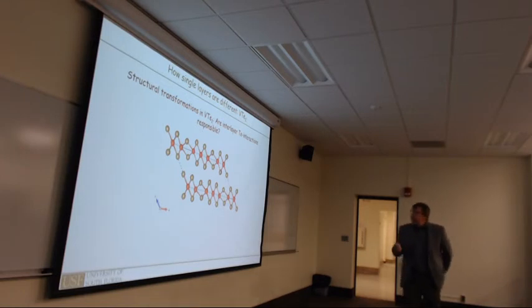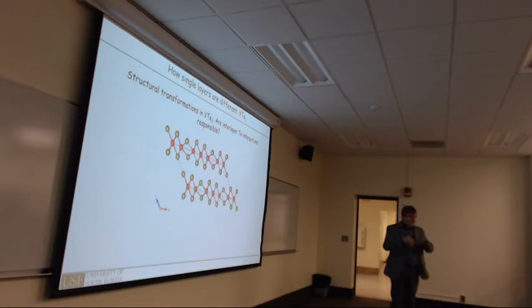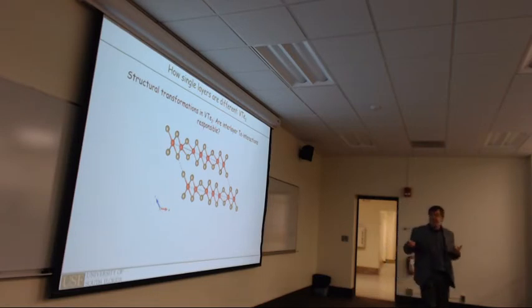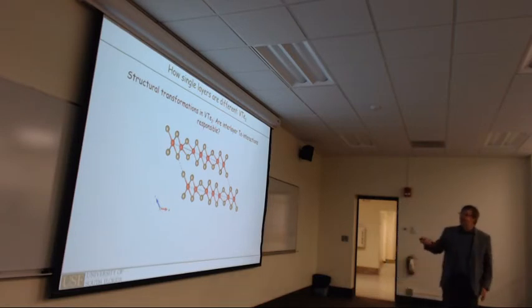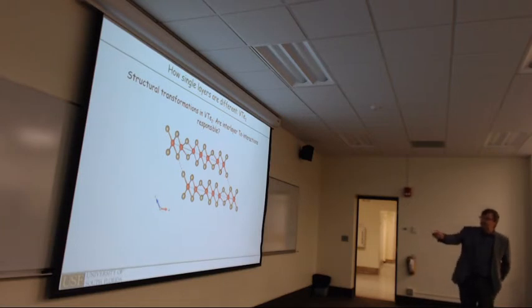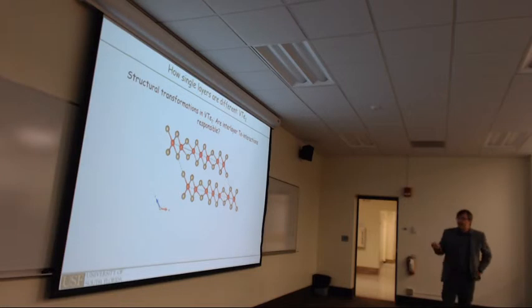And so we were interested in this material, vanadium ditelluride, which in the bulk doesn't have a simple structure like the molybdenum disulfide, for example, but has this additional structural distortion in the unit cell. So every third row of tellurium atoms are squashed together, and then they stack on top of each other, making this monoclinic unit cell.